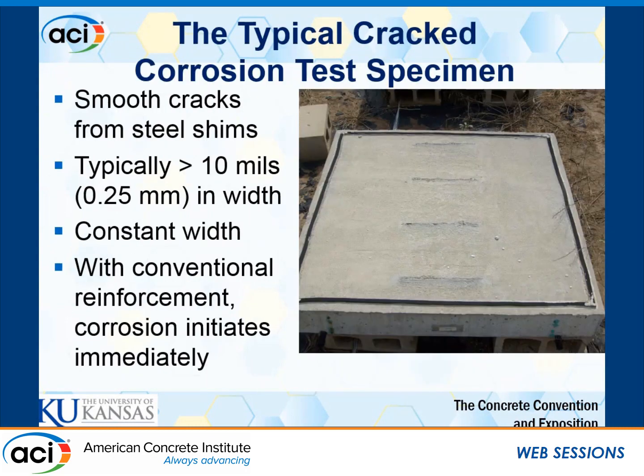Moving back into the corrosion lab, we have a number of specimens that we've looked at. We test those both in cracked and uncracked conditions. The thing to note here is for our cracked concrete, we want to control that variable as best as we can, so we have a fixed crack length and width. So in our case, at KU, we use 12 mil wide fixed length cracks that we put directly over those reinforcing bars with stainless steel shims. And with our conventional ASTM A615 black bars, we see immediate corrosion initiation.